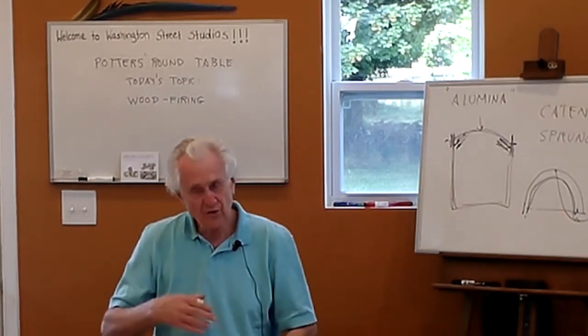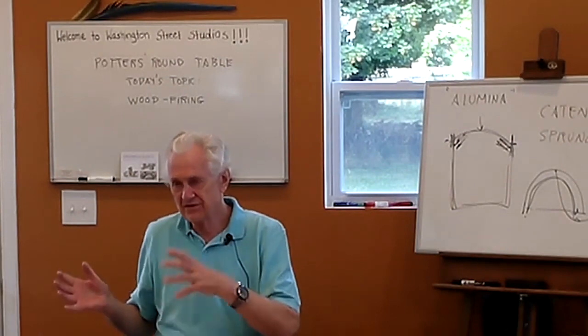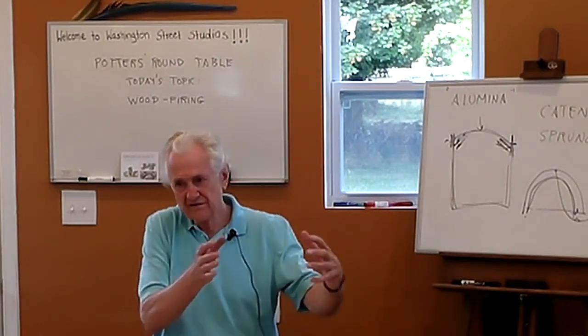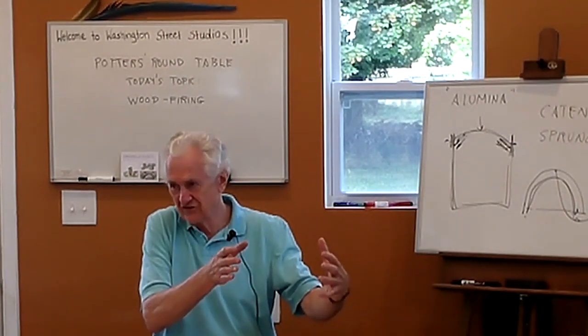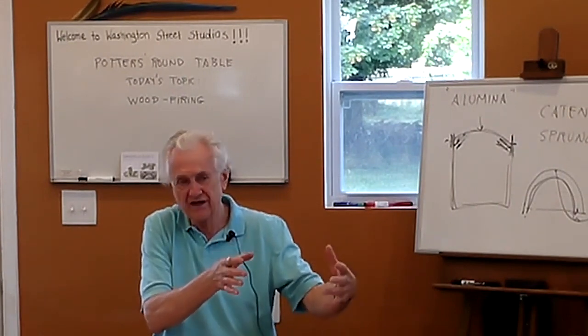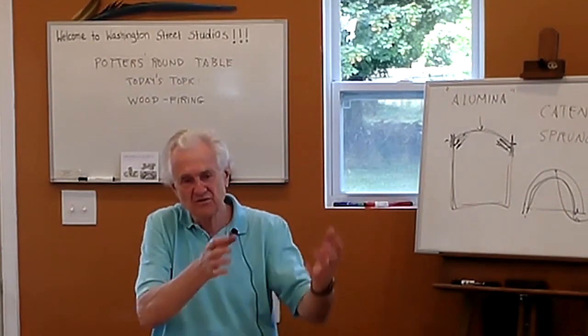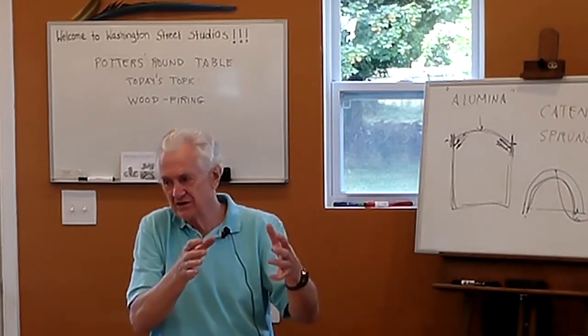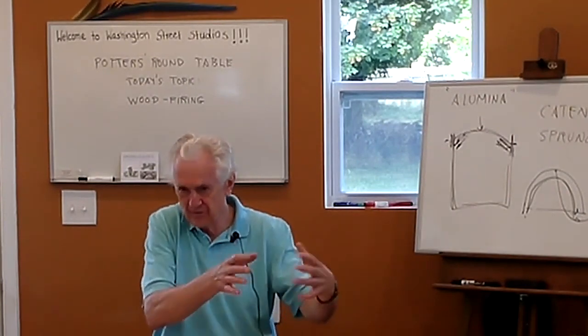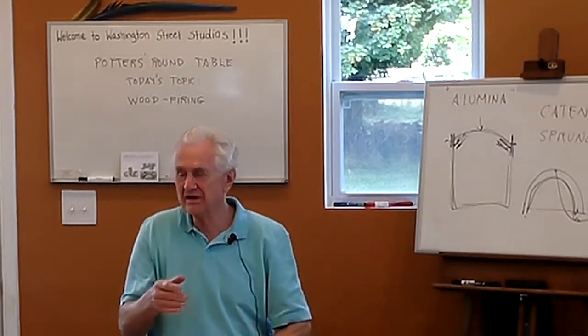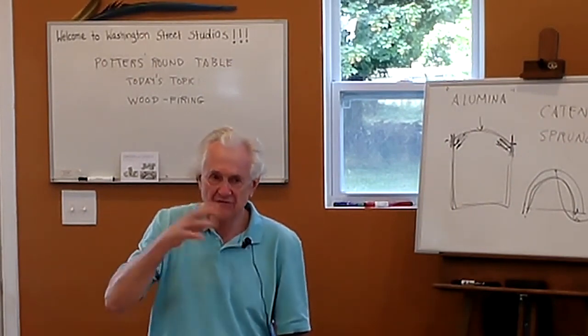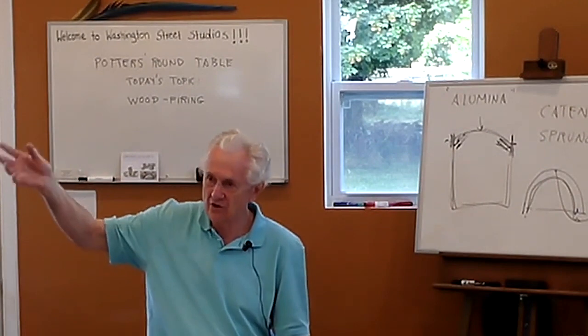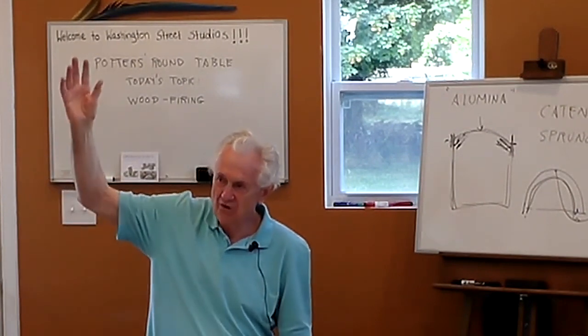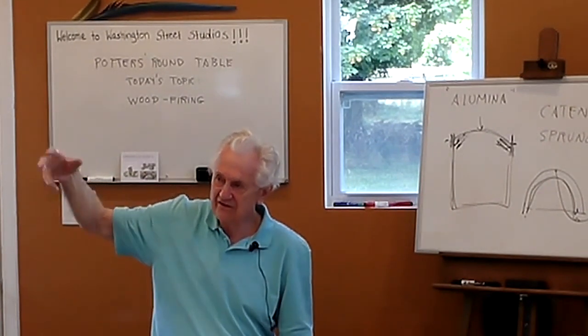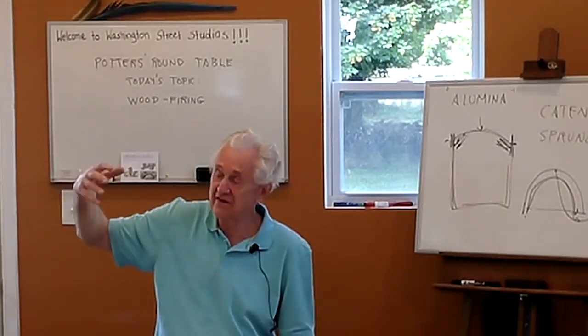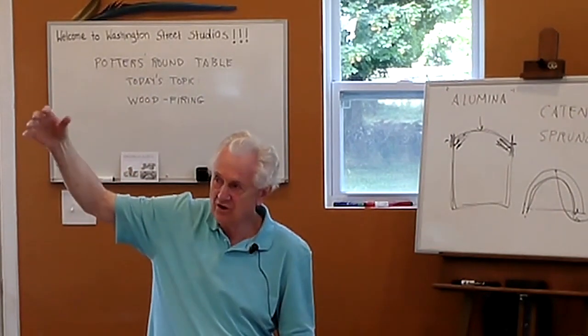forth. So when you're firing a wood kiln, typically, when you do a stoke, you go into a very heavy reduction before that wood actually sort of catches fire. And you're cooking the flame. And then when it catches and it's burning vigorously, then you go into a lighter reduction. You're getting more efficient burning. So typically when you're firing a wood kiln, you're going between heavy reduction and lighter reduction. Every time you stoke, you go into heavy reduction and you get a lot of smoke out of the chimney. And then it sort of clears and the wood really catches and burns. And then you get the most heat and then you go into a lighter reduction.